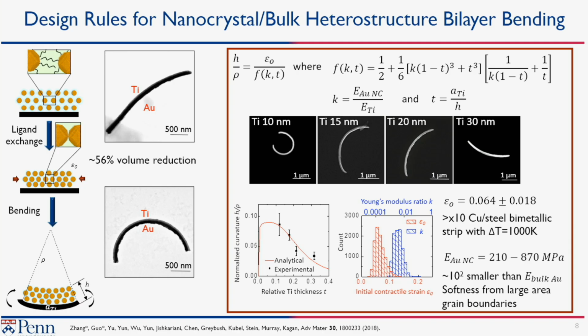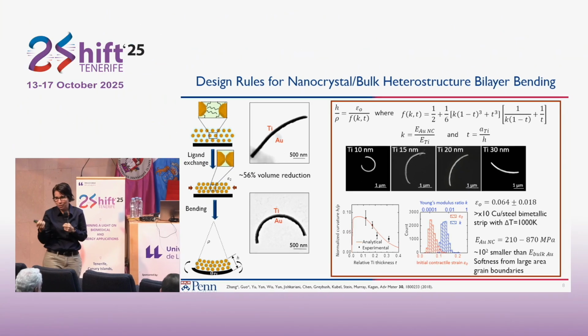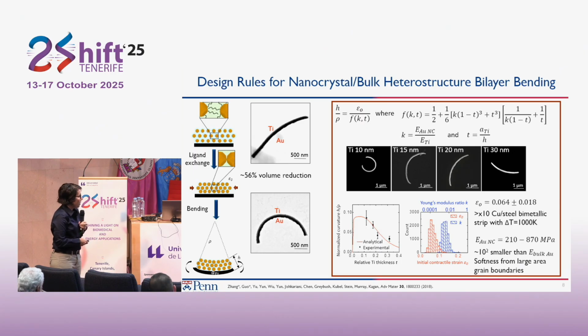The only other things that are actually in this equation are the Young's modulus of the nanocrystal layer, which we don't know, the Young's modulus of bulk titanium, which we do know, and the thicknesses that we measured. And so we made a lot of these, and could do statistics on them and fit this to a model. What we could learn from this as an upshot is that just by simple chemical approaches, 30 seconds immersion in a solution, for example, we could generate misfit strains of about 6.4%. That's 10 times more than when you heat a copper steel bimetallic strip by 1,000 degrees.